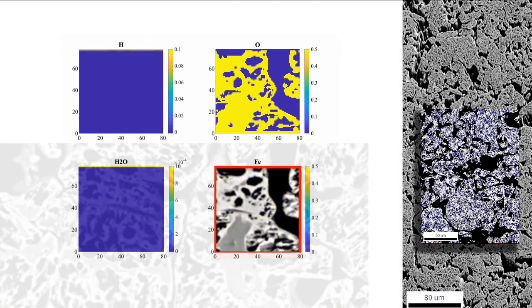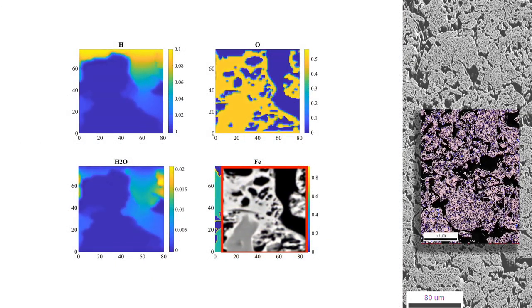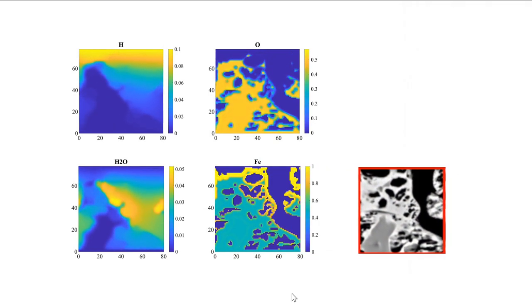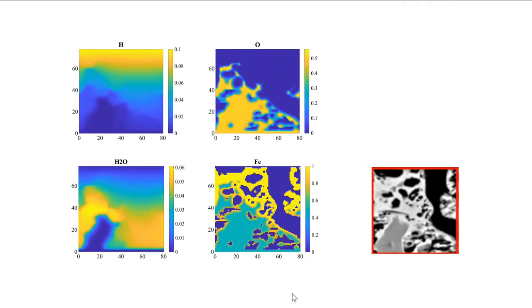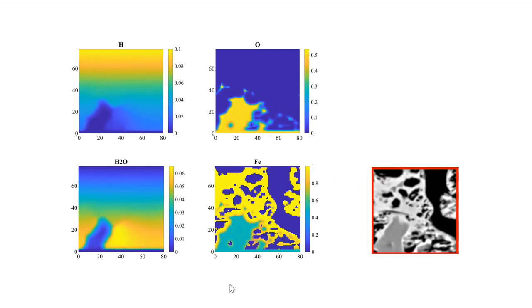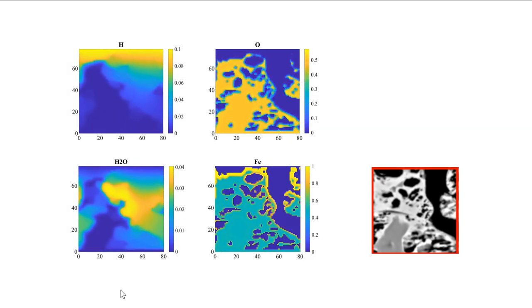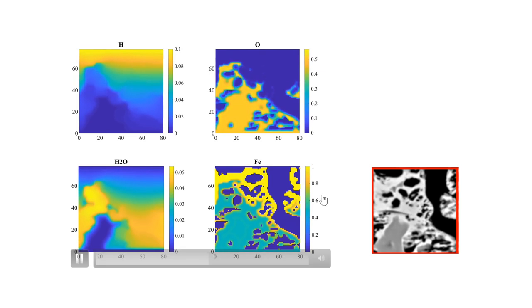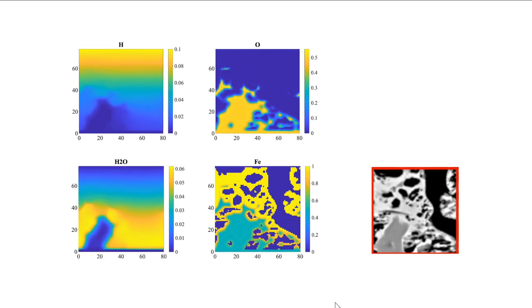Now we are interested also in subjecting them to a boundary condition treatment through a corresponding phase field calculation. And in this phase field calculation, you can see the diffusion of the hydrogen, of the oxygen, and you can see the formation of the water as a reaction product. In this diagram, you see how the iron is starting to penetrate the former oxide.